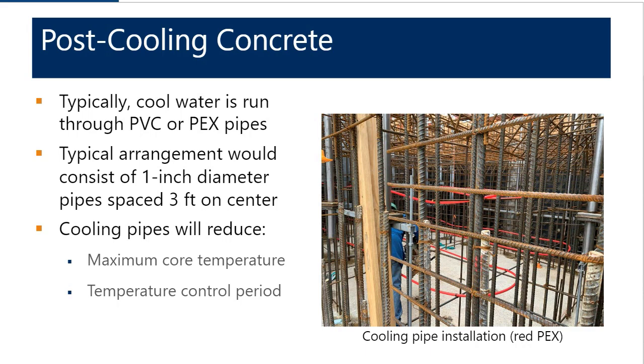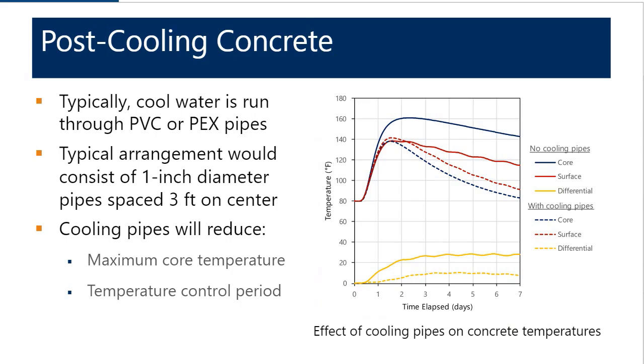So you can either use PEX pipes or PVC. If you use PVC, you would typically use a 1-inch diameter, and you want to space those about 3 feet on center. If you space them anything greater than that, it has a diminishing cooling effect, and oftentimes the startup costs don't justify the minimal effect that it has on cooling the element. And so the nice thing about cooling pipes is they will reduce the maximum core temperature, and they'll also reduce the temperature control period.